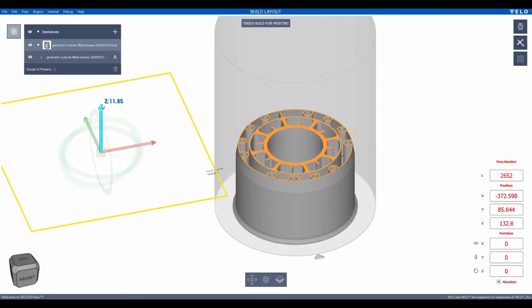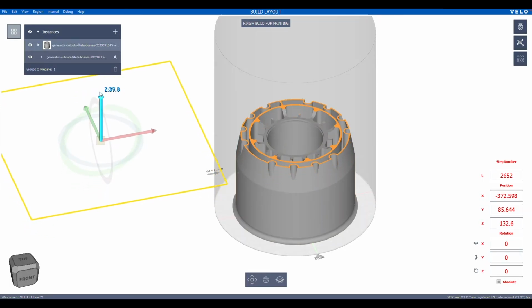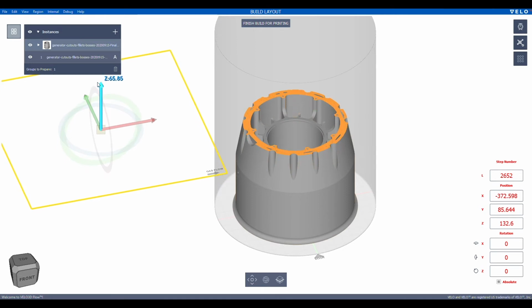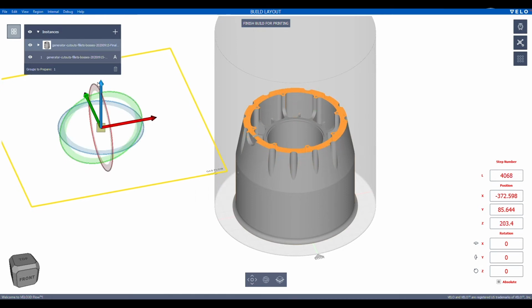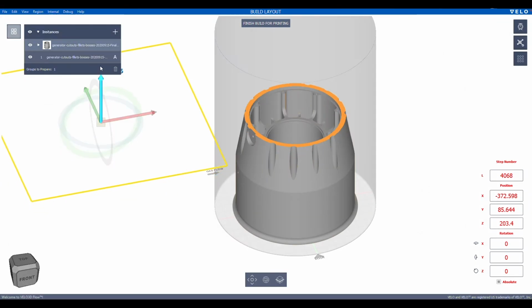Then lastly, these internal cavities close out without any added support material. Again, they get a specific laser parameter so that we don't have any real degradation of surface roughness at that closeout, as well as no need for added support material that in this case would be impossible to remove.